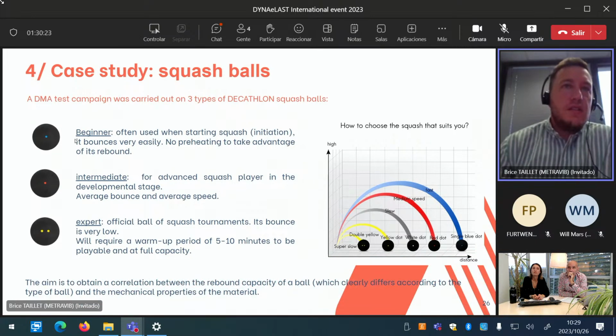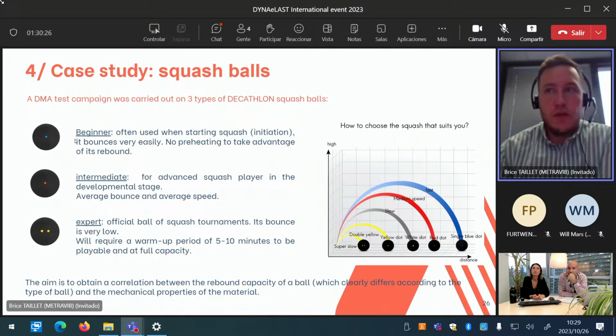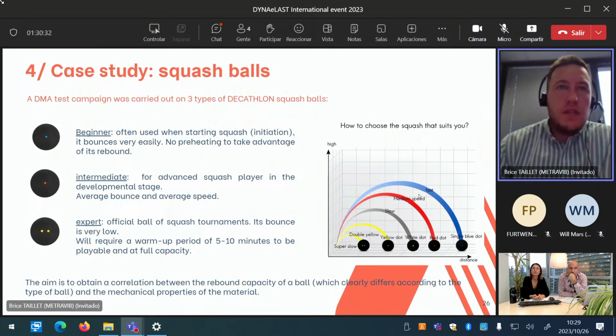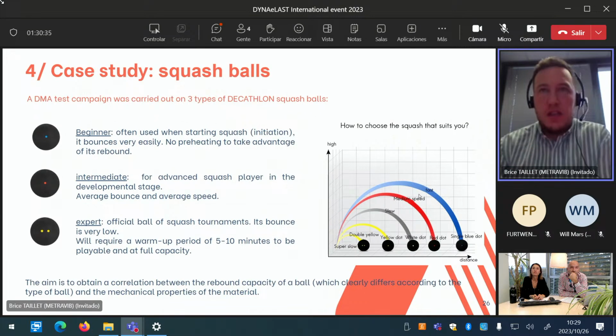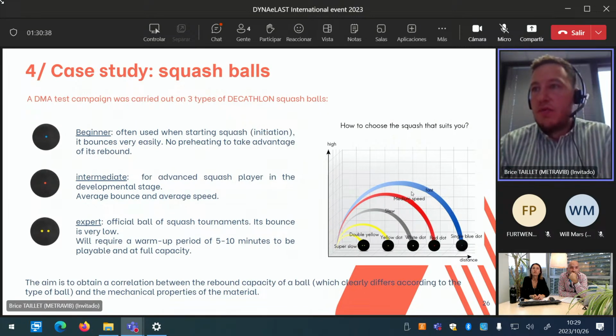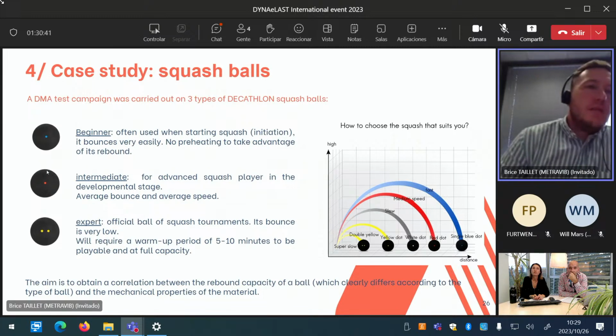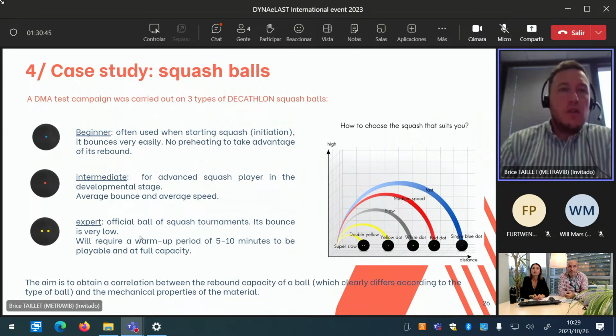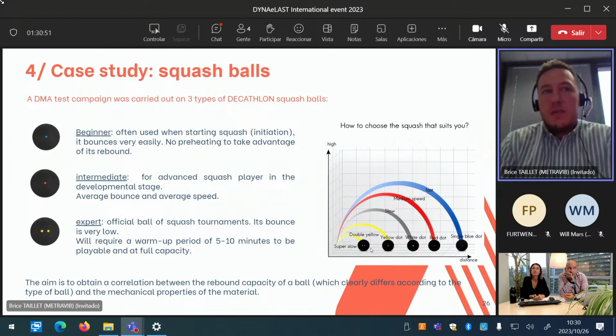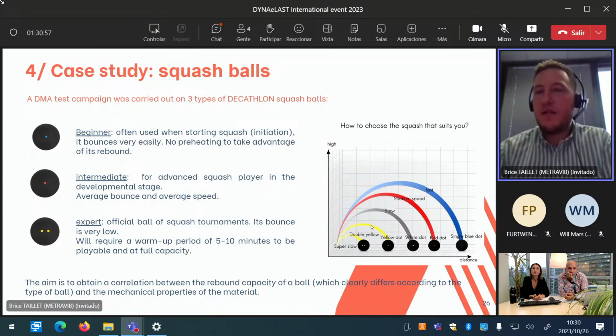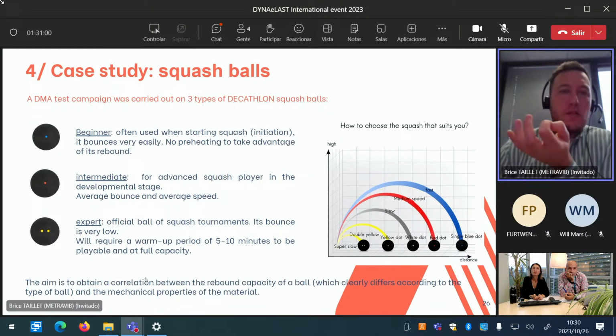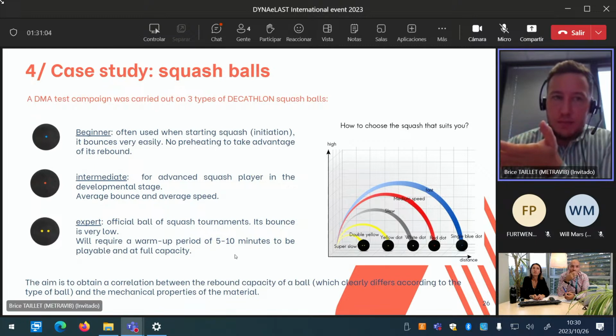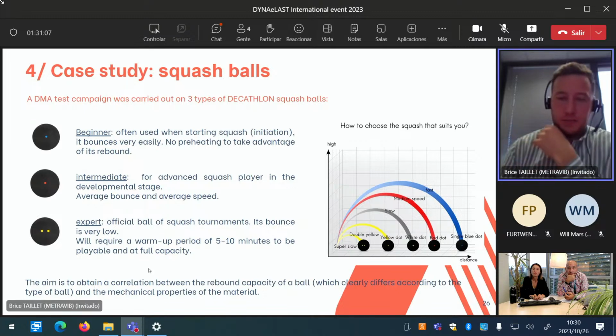configuration. The beginner is really often used when you're starting squash for initiation. It bounces really easily, and we don't need to preheat the balls before taking advantage of its rebound. As you can see on the blue curve, the rebound is quite high. As the opposite, the expert is the official ball for squash tournaments, and its bounce is really low, and the expert ball requires a warm-up period of 5-10 minutes to be playable at its full capacity. So the aim is to obtain the correlation between the rebound capacity of a ball and the mechanical properties of materials. For this,